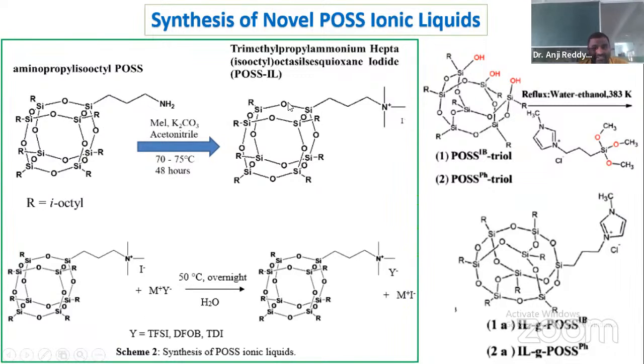First we synthesized this one, which is one of the basic ionic liquids. By using this basic ionic liquid, we synthesize different types of ionic liquids by changing the anions. This iodide anion we can replace by TFSI, DFOB, or TDI. All these three we synthesized. We use these ionic liquids in our polymer electrolytes, and that increases conductivity and mechanical stability simultaneously.